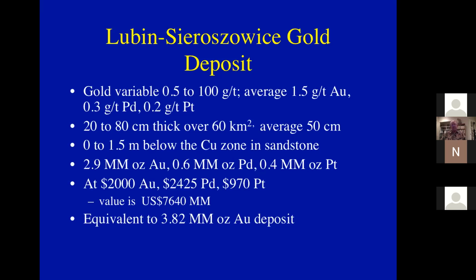Now that's a huge but very thin gold deposit. It's between 0 and 1.5 meters below the copper zone, largely in the sandstone. And when you calculate some reasonable assumptions about tons and grade, you get something like 2.9 million ounces of gold, 0.6 million ounces of palladium, 0.4 million ounces of platinum. And at current mining prices, it has a value in the ground of something like $8 billion. And it's equivalent to basically a 4 million ounce gold deposit.